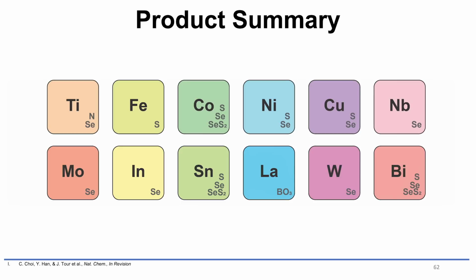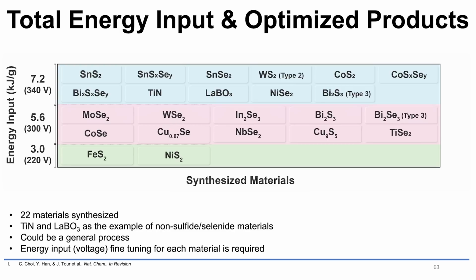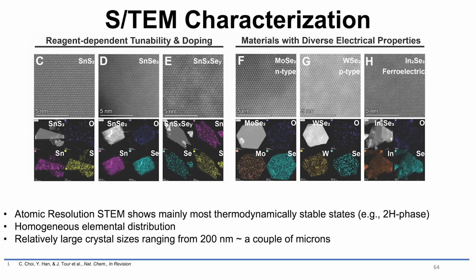And so here's all the different products that we've made. We've made titanium nitride, titanium selenide, iron sulfide, cobalt sulfide, and so on. So we've made all of these different materials. We've made 22 different materials that were synthesized. We've made non-sulfide, non-selenide materials. We've made a number of 2D materials, these transition metal dichalcogenides, these TMDs. So you see all the different materials that could be synthesized. And these are really clean materials. So for example, here's the characterization of a lot of materials. You see how clean these can be, and this is all in aberration-corrected TEM. And you see how clean the materials can be.